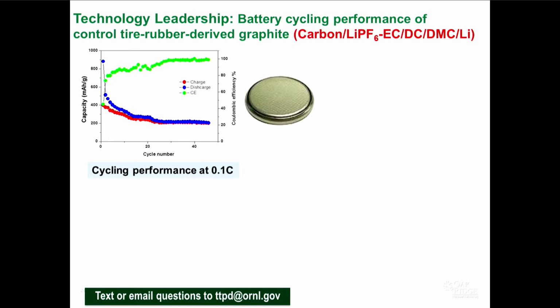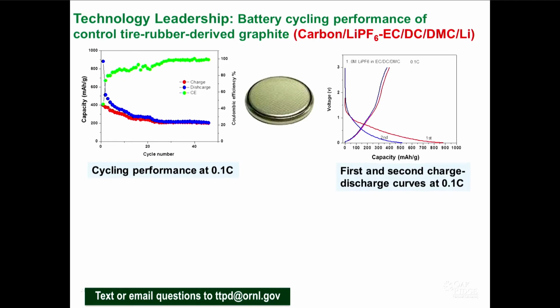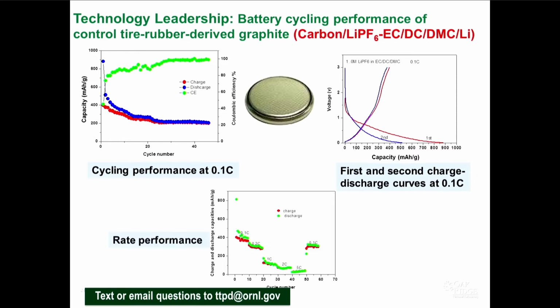So we saw in the case of commercial graphite over 350 to 360, the theoretical limit for graphite is 372 milliamp hour per gram. Whereas here, it's 200. And if you look at the first and second charge discharge curves at 0.1C, we have a huge drop, and that means you have a reaction between the anode and the electrolyte. And if you look at the rate performance, the capacities at 2C and 5C are really low. So you couldn't use this control sample. To summarize this material, controlled tire-derived graphite has capacities of like 200 milliamp hour per gram after 45 cycles. So let's look at what we have with sulphonated tire rubber derived graphite.